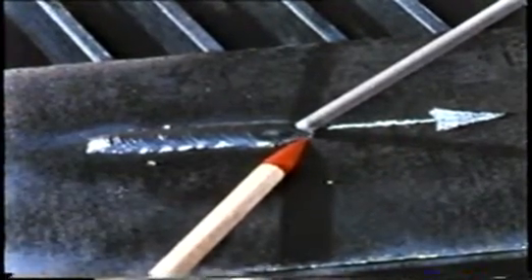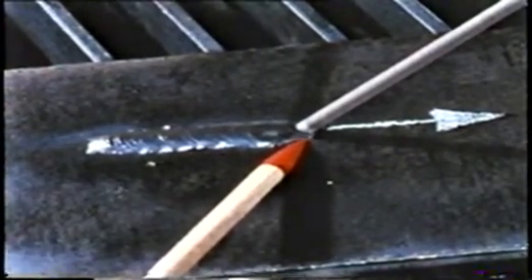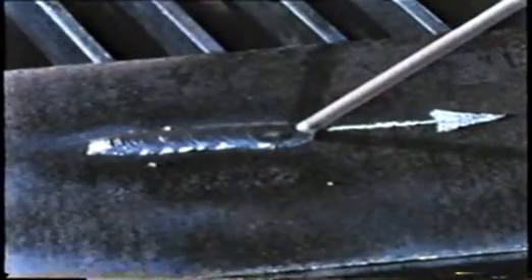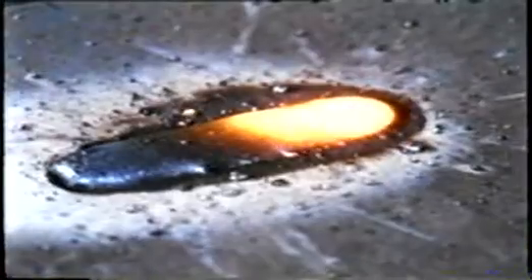Avoid watching the arc itself at the tip of the electrode, even though protected by a colored welding lens. Make sure the red color has disappeared from the weld bead before chipping the slag from the weld. Too early an exposure from the surrounding air will absorb oxygen and nitrogen, which is apt to cause weld contamination. This slag, formed by some of the substances in the chemical coating, floats out the impurities in the molten metal and forms a protective coating to prevent oxidation.